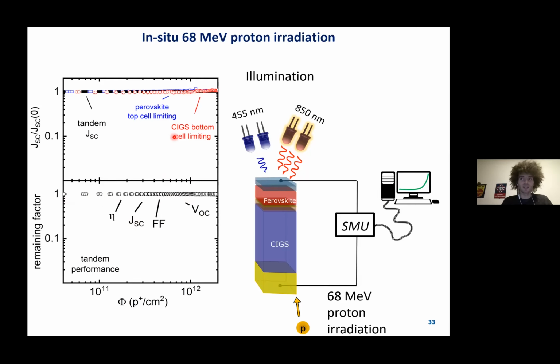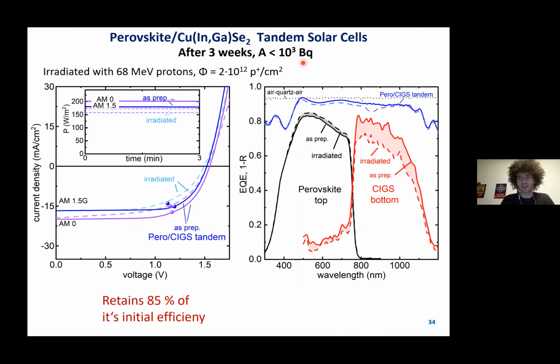So this looks promising. We don't need perovskite silicon tandems. We can just use a perovskite CIGS. After irradiation, so after the activity dropped to a safe level, I again measured all tandems under AM0 and AM1.5, and there I saw a little bit of degradation, and it retained around 85% of its initial efficiency, mainly because of some damage in the CIGS subcell. However, again, there were some artifacts when measuring EQE, and these are related to defects in the CIGS. And so under the right measurement conditions, we could recover the original EQE here.